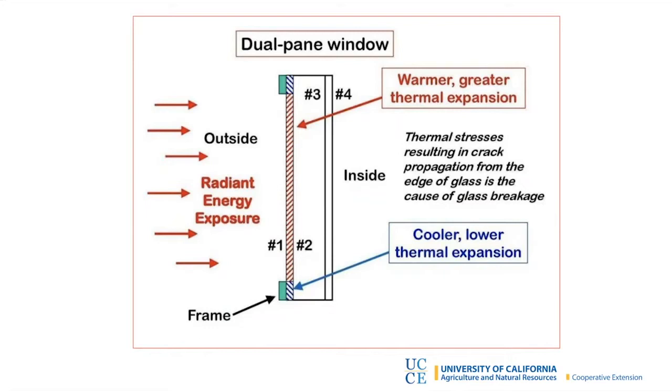And then, whatever framing material you're using, that's the green part. Glass is vulnerable because of the protection offered to part of the glass by that frame, compared to the part of the glass that is completely exposed to either the flames or the radiant heat. In this picture, we're looking at radiant heat. Part of the glass gets hot, and the part of the glass protected by the frame doesn't get as hot. So you have a temperature difference between the exposed glass and the protected glass. It's these temperature differences that result in stresses that cause small cracks or fractures at the edge of the glass to expand and move into the part of the window that's not protected by the frame. If you have enough of these cracks occurring, then the glass breaks and you can have glass falling out.